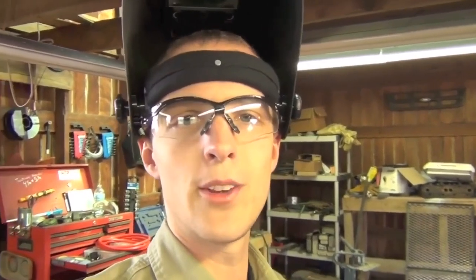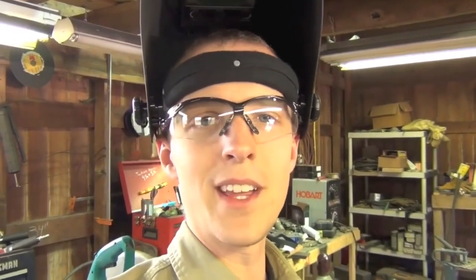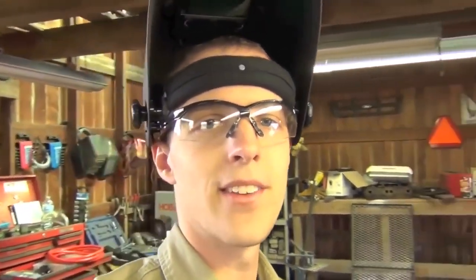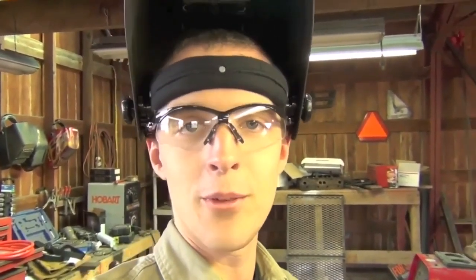Now, what a lot of people have issues with is what's known as cold lap, or running too cold, and this is because MIG welding can be a little bit deceiving. If you're stick welding something and you put down a weld that's way too cold, you take one good look at it and you know it's way too cold. But when you're MIG welding, looks can be deceiving. MIG is notoriously famous for putting down a really good looking weld with very little penetration, very little fusion, very little tie-in, and because of that it's weak and it will fail and possibly have disastrous results. But there are a few surefire things you can look at to identify that while it's going on or after you've done it, and that's what I'm going to show y'all.